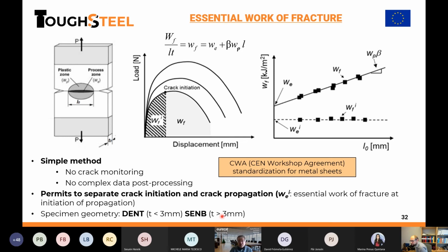Yeah, I think again, we are working on this so that the sector is using it. We have different projects with steel makers, with part makers, with car makers, and I think the idea is really reaching this. In fact, ToughSteel has in the partnership the different steel associations in Sweden, Italy, and Spain. So the idea is this, and they can really do it in production, because here you see that these tests look quite complicated. We have a notch, a crack to propagate and nucleate and then test it. It takes some days, as Laura will say in the next presentation, but we developed a method that you can do very, very fast and easy. This is some presentation of that.